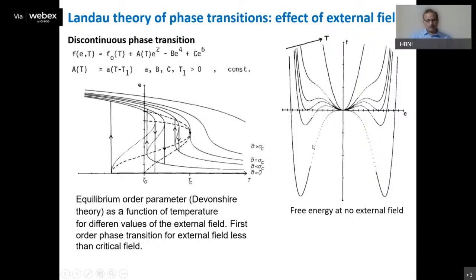Now let us see what happens to this order parameter versus temperature plot when you have different stress values. So this curve basically shows the transition when there is no field. Up to a certain temperature, you have the initial phase, and then suddenly your order parameter changes and follows this way. This is a signature of first order phase transition when there is no field.